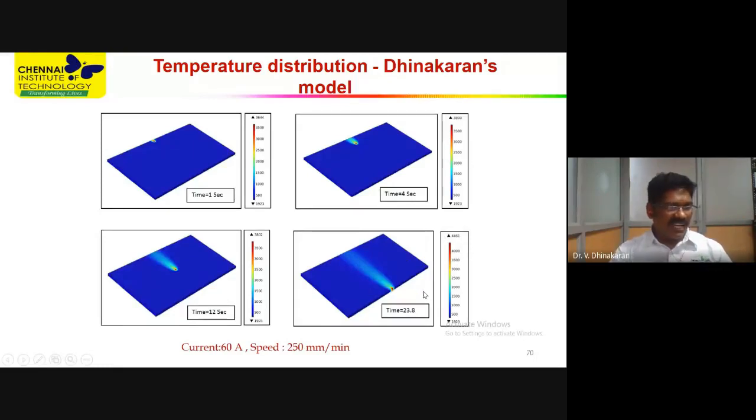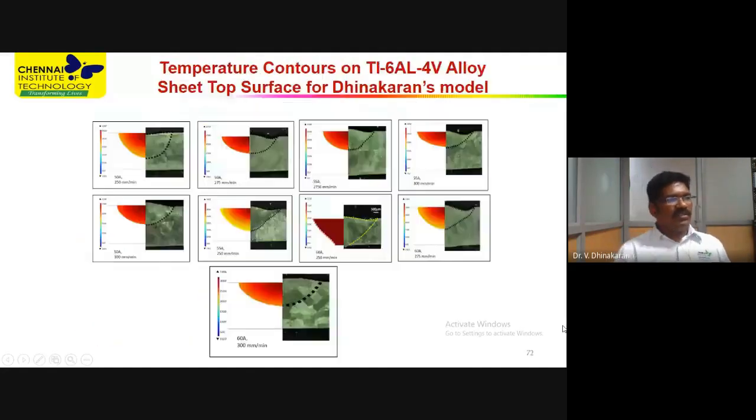The reason for the sudden increase of temperature is that while the heat source is here, there is area normal to the surface for heat transfer, but here there will be no area for further heat transfer enhancement. Hence, the temperature is suddenly rising from the constant to a certain extent. Okay, so see, this is the experimental macrograph obtained from the experiments, and these are the macro profiles predicted from the computational mechanics, and see both are almost matching with the experimental results.